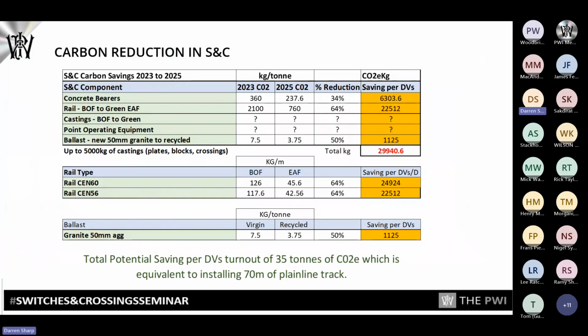For the carbon in S&C, we broke down the individual parts into the bearers, the rail, the castings. There's still some areas we don't know. We don't know point operating equipment carbon equivalents. We do for ballast, we do for rail, we do for concrete, because we're doing that for plain line, so we can apply those low carbon concrete mixes for S&C as well. The green rail for S&C and castings, and also there's some work there to be done on recycling ballast. So if we employ the low carbon concrete and green rail, we can actually have a reduction there, you see, of 29,000 kilograms of CO2 for a DV switch, which is quite a lot of saving.